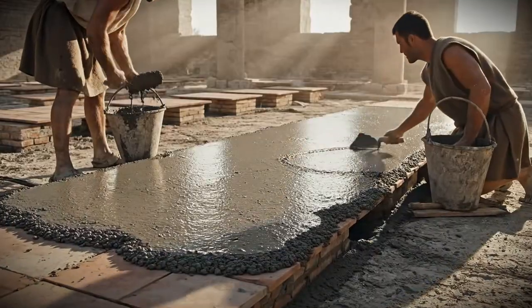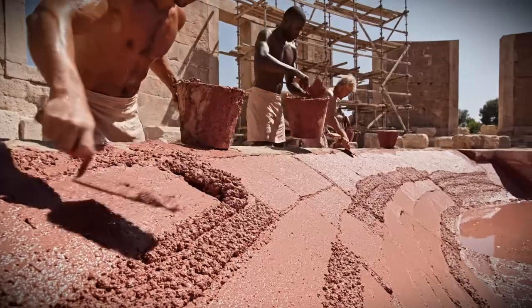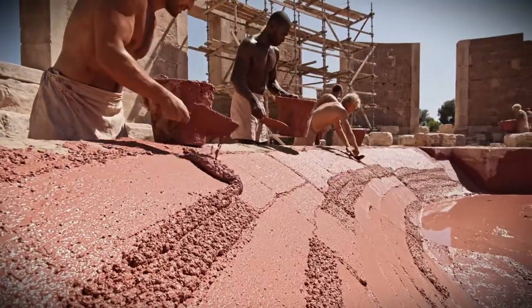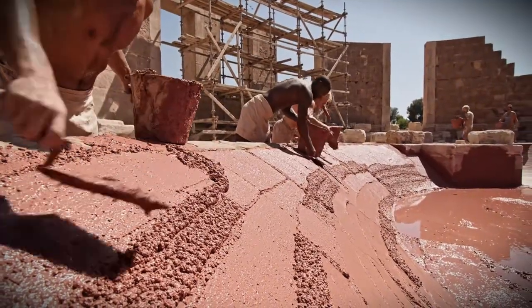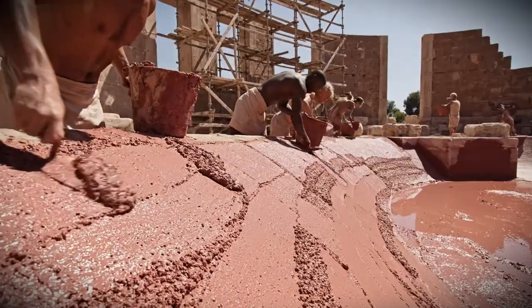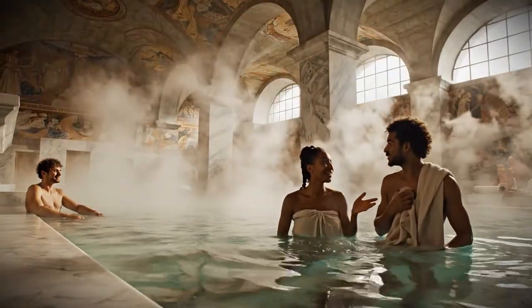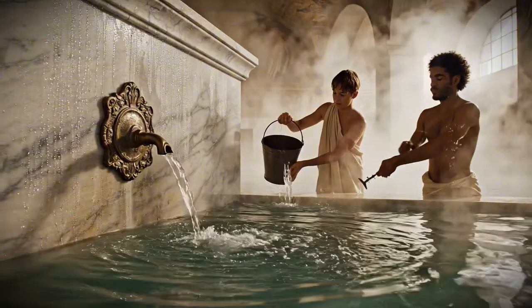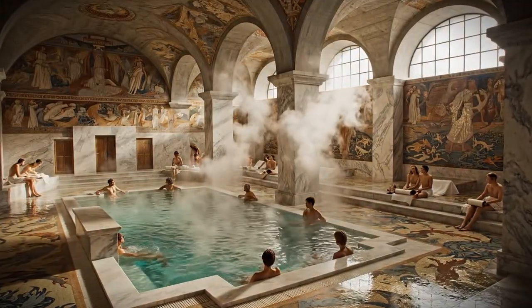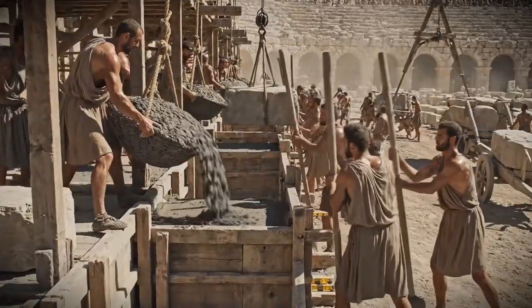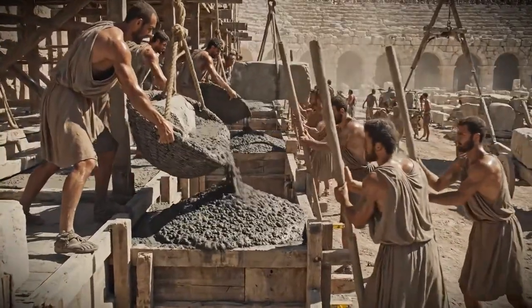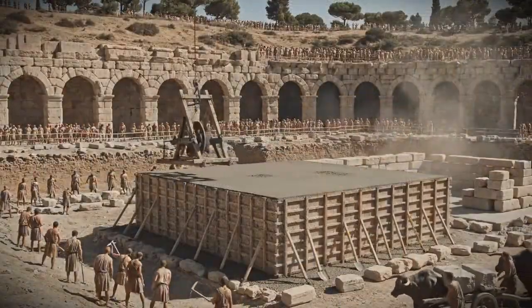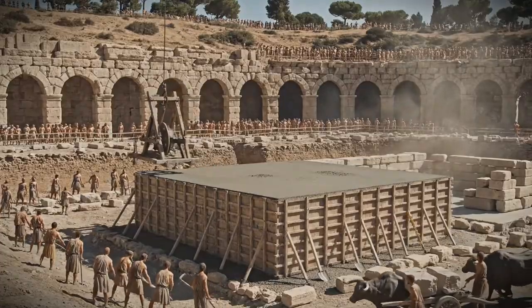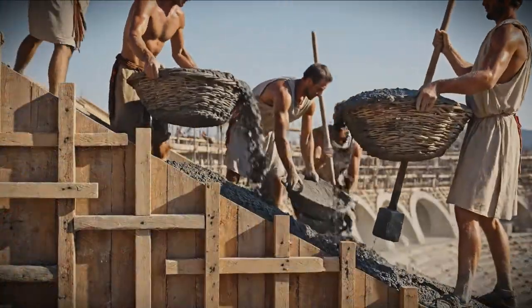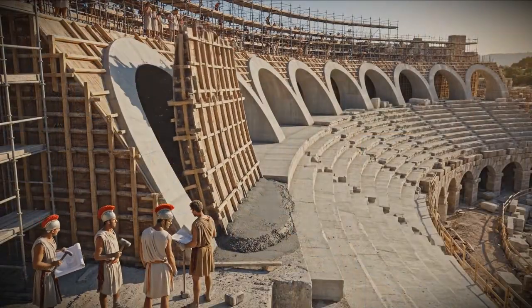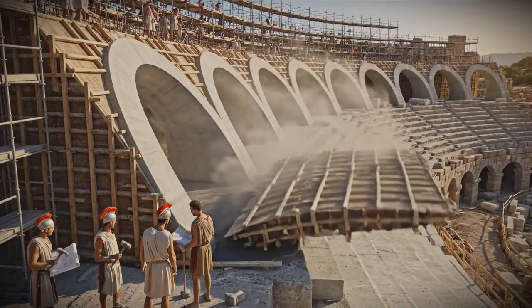The construction process for marine concrete was elaborate and fascinating. Since they couldn't pour liquid concrete underwater, the Romans developed a method using wooden cofferdam structures. They would drive oak pilings into the seabed in a double ring, creating a watertight enclosure. The space between the double walls would be filled with clay to prevent water infiltration. Then they'd bail out the water from the interior, creating a dry workspace below sea level. Within this temporary dry dock, they'd construct their permanent concrete structure using the special pozzolana mix.